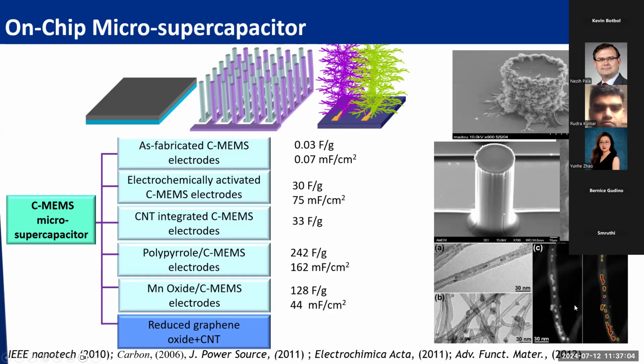And we also have different research trying to modify carbon nanotubes. For example, the picture here shows carbon nanotubes can be grown directly on the carbon micropillars by two different methods. One method, we mix with a catalyst. So in my group, we mix iron particles into the photoresist. During the carbonization, we see this redeposition of the carbon species as a one-dimensional material onto the glassy carbon. So we have the high surface area carbon post coated with these carbon fibers.